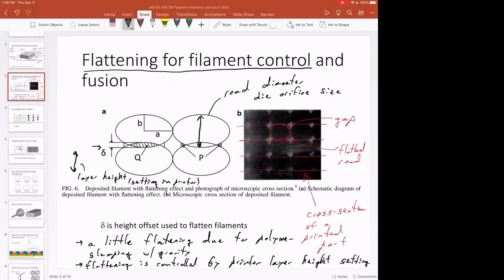But you often get these gaps. If you look very closely at an FDM part, you see the lines on the surface of the part, but if you cut the part open, you can also see the gaps between the roads. And these gaps don't have any mechanical properties. You know, it's air. This lowers the density of the polymer as well. And so if you have less material in your part, it's naturally going to be weaker. And then you have all these interfaces where the part can crack. If anyone has ever made a part using material extrusion AM, you know that layer adhesion is important. Sometimes you make a part and it's really easy to break between layer 5 and layer 6, or between layer 10 and layer 11 because that layer is weak. And so this starts to give us some tools to think about how you might accomplish good material extrusion AM and what some of the parameters are.